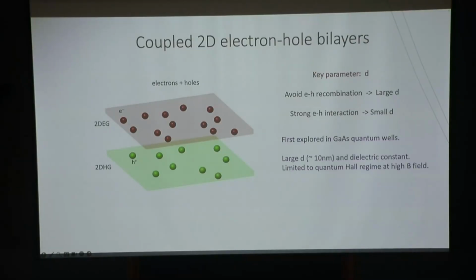So the first experimental trial of this bilayer system started when we had gallium arsenide quantum well structures, where you can grow these heterostructures in a pretty well controlled way. However, due to the material limitation, the smallest d that we can use in this conventional semiconductor heterostructure, to prevent the electron-hole recombination, needs to be larger than 10 nanometers. Although this sounds like a pretty small distance, compared with atomic thickness, it is already pretty large. And then combined with the relatively large dielectric constant of gallium arsenide, at the end, the attractive Coulomb interaction of the electron and hole remains rather small. So at zero magnetic field, you can barely see this exciton physics.